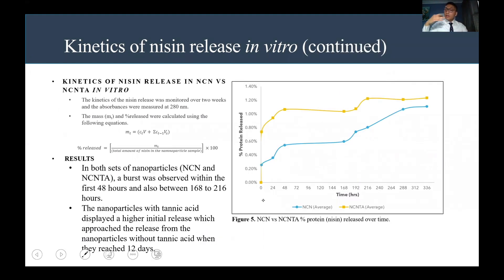After examining the NCN release kinetics, we compared them to the average of the tannic acid nanoparticles. We observed a burst release within the first 48 hours, and another burst at 168 to 216 hours. This shows that the nanoparticles with tannic acid displayed a higher initial release, which approached the release from the nanoparticles without tannic acid around 12 days.